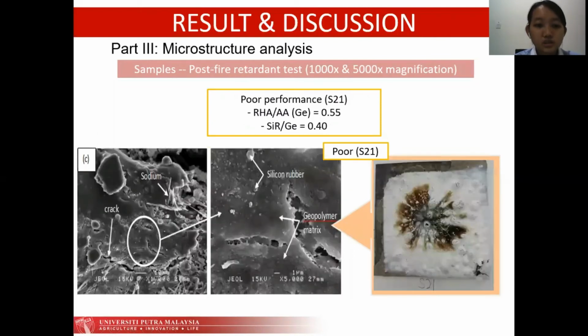So this is the sample after the fire test. It showed the formation of long and wide cracks in the residue. As the coating was heated, the air inside the coating swelled and expanded the cracks. This is because the insufficient silicone rubber in the sample does not significantly help in providing additional protection for the substrate.